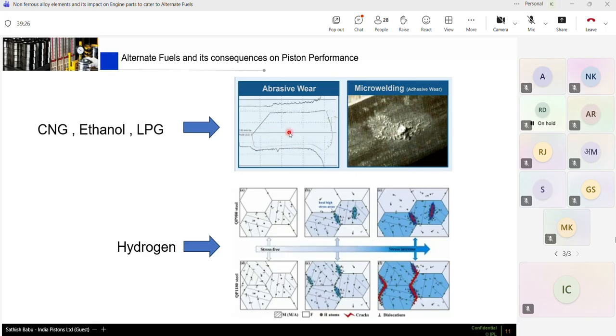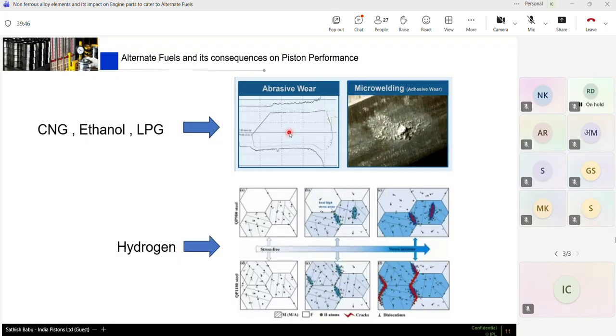these parts, because the oil which is supposed to guide the piston rings and piston, with some amount of friction, should be there. It is supposed to be a hydrodynamic or mixed lubrication, but it is not. It is a dry lubrication. Because of this dry lubrication, the piston is getting eroded, and a lot of aluminum particles get stuck on the piston rings. That we call adhesive wear here. So to avoid this, of course, we have materials which we can explain in the coming portion.